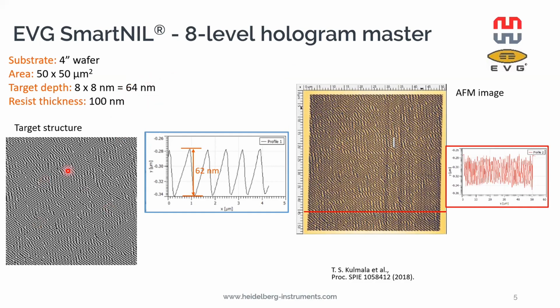The target structure is seen here on the left, and the actual structure written in the PPA is seen on the right. From the AFM images, we can see that the depth of the pattern corresponds very well to the target depth, and it is also uniform throughout the entire pattern.